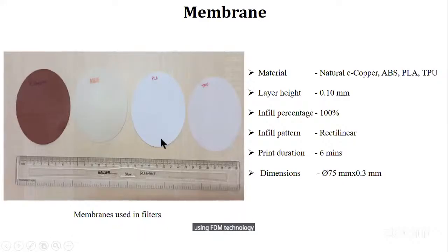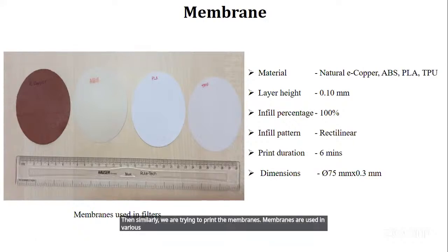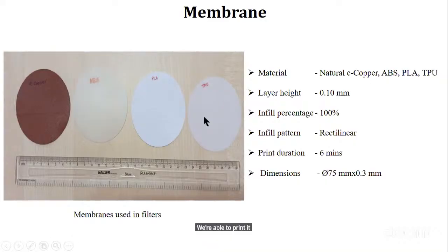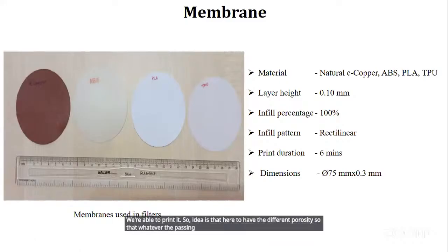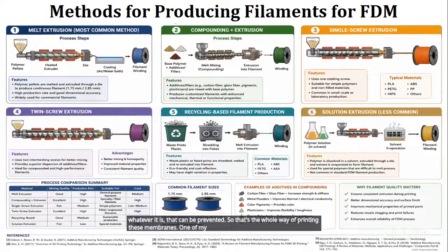Then similarly, we are trying to print membranes. Membranes are used for various purposes like filtering, in e-copper, ABS, PLA, TPU. The diameter is around 75 millimeters and the thickness is 0.3 millimeters, with only 2-3 layers of printing. So we are able to print it. The idea is to have different porosity, so that when water is passing, different particles, water, chemicals, whatever it is, can be prevented. That's the whole idea of printing these membranes. One of my colleagues in chemical engineering tried it for his work.